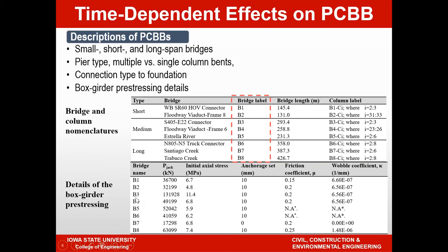The details of the box girder bridges are shown here, so there are some variations to observe. The initial axial stress, as I said, that's the pre-stress, is not constant in these bridges. They vary between 4.8 megapascal to 11.4 megapascal. That's the information that we found from the design details of the design drawings. The anchorage friction coefficients are all specified in the drawings, and the same applies to the wobble coefficient. All of these reported values were used respectively for each and every bridge analysis.